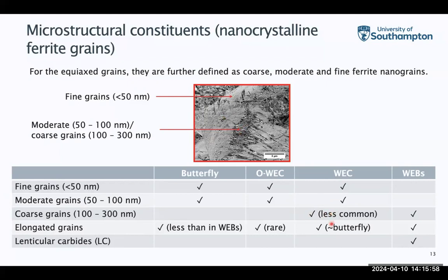So you can see here, most of them are fine grains and moderate grains, but the coarse grains are very small amounts. All three have elongated grains, but they are not so many compared with the white-etching bands, as I showed you earlier. For the white-etching bands, most of the grains are the coarse grains and the elongated grains. Also for the white-etching bands, they have what we call lenticular carbides.